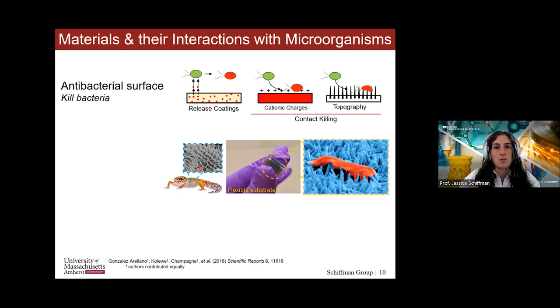And so in this one example, this collaboration, we were inspired by nature. We tried to mimic the backs of the geckos that have these long hairs, and they actually have these sharp corners. In this case, we grew these inorganic materials. And again, the bacteria, in this case Pseudomonas, was much more effective at being killed by this structure because it would crawl across it. When we used this structure against a different bacteria like MRSA, which is spherical, like a grape, we did not have as much inactivation.